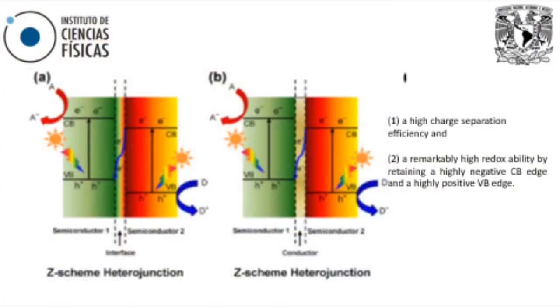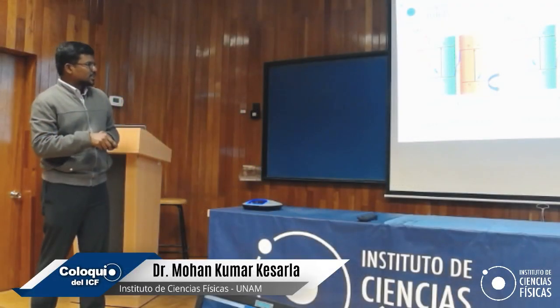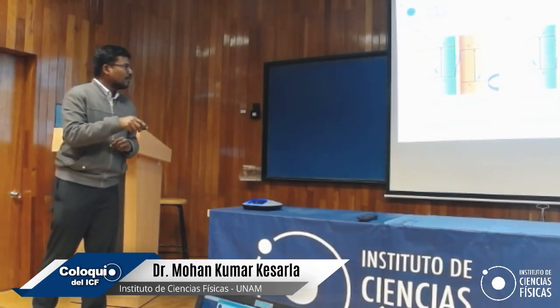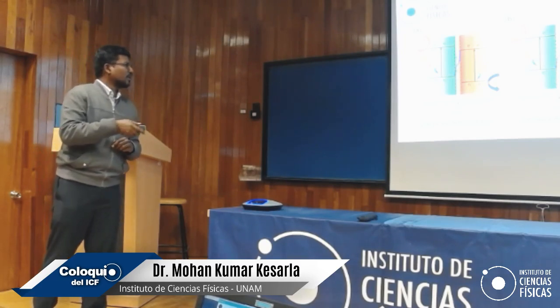So it looks like a type 2 semiconductor, but the charge transfer is very different. The conduction band electrons in semiconductor 2 will travel to the valence band holes of semiconductor 1. The good thing here is you are not changing the potential of the conduction band, and you are not changing the potential of the valence band. So the reduction and oxidation occur very safely. So no problem with this kind of junction. And there are two types of Z-scheme semiconductors, where we have an interface conductor for effective transfer of electrons also.